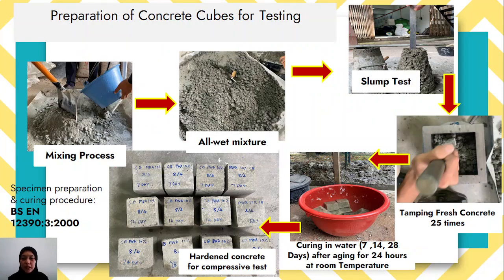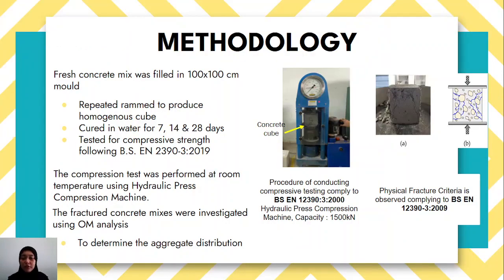All the specimen preparation and curing procedures follow the British standard. Fresh concrete mix was filled in 100 x 100 mm molds and rammed to produce homogeneous cubes, also cured in water for 7, 14 and 28 days. After that, it was tested for compressive strength following the British standard. The compression test was performed at room temperature using a hydraulic press compression machine, and the fractured concrete mix was investigated using an optical microscope. This analysis is to determine the aggregate distribution.